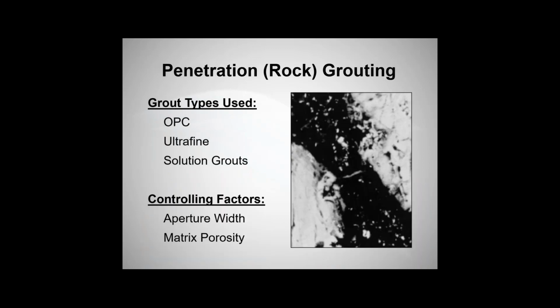So what are the grout types typically used for penetration grouting? Ordinary Portland cement is going to be the first and foremost. We just saw that in the poll probably. And that's why it's probably used 95% of the time in all grouting applications for 2 reasons. One, the geology will accept it. And secondly, from a cost perspective. Once the geology may tighten, we oftentimes shift to an ultrafine cement. And in some situations like matrix porosity, a solution grout would be used.